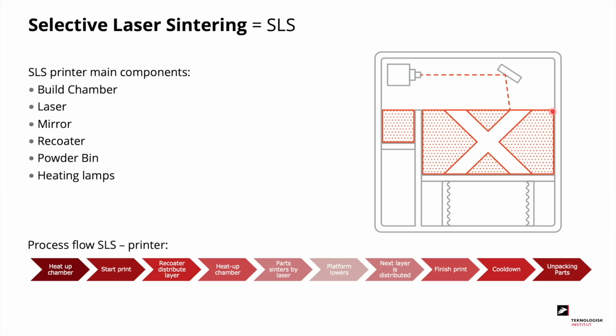Some of the most typical print parameters for selective laser sintering would be printing in PA12, one of the most common materials in SLS, printing about 0.1 millimeters in layer thickness, and heating the entire chamber to about 180 degrees, just below the melting temperature, and then with maybe a 40 to 50 watt laser sintering together these particles.